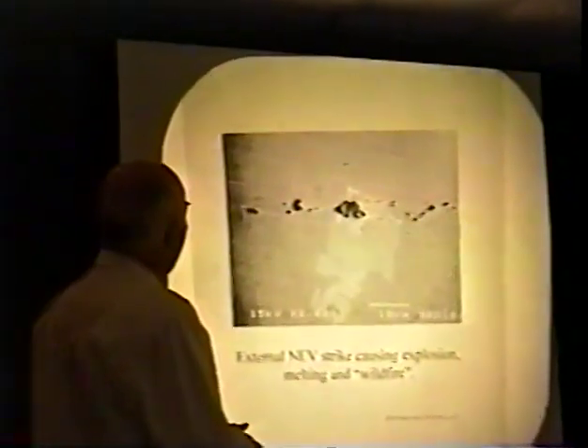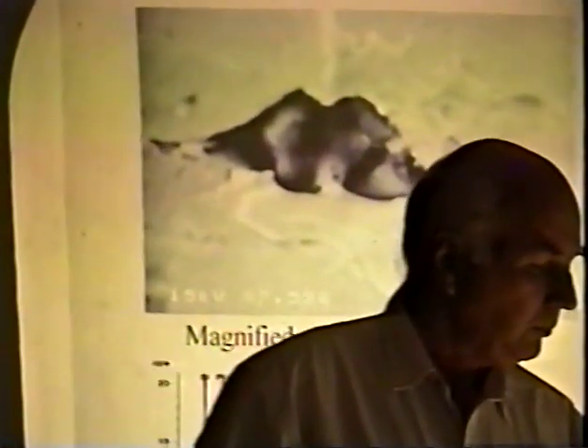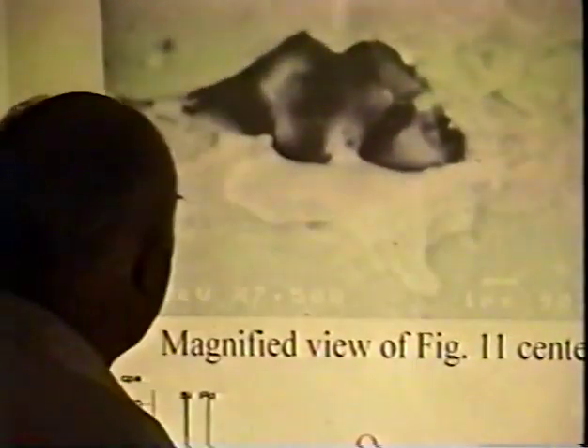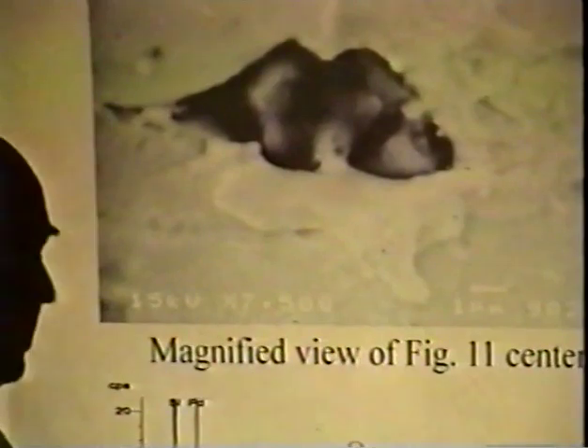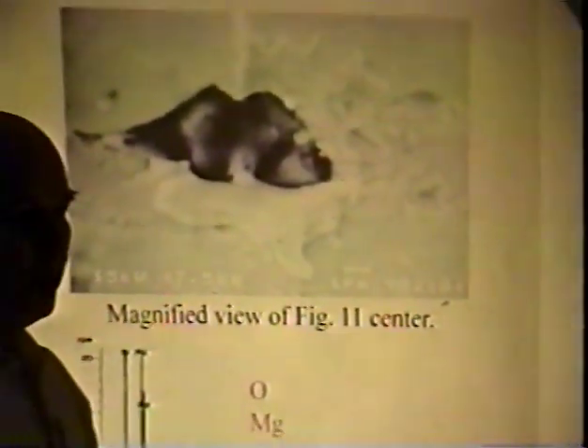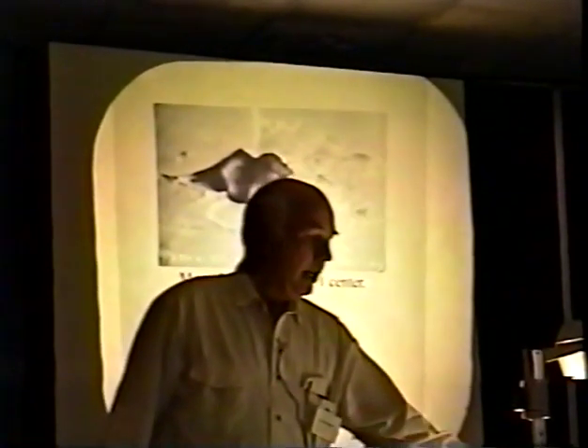Now, it's more evident in things like this, where you purposely bombard the surface, analyze this particular area, you'll see there's something happened here, some kind of little spreading of energy. Not trying to define what it is in this talk. I'll say when you get up and closely analyze that particular sample, look at that trash pile here. You'll see there's a lot of melted laid-back material, and what you find is oxygen, magnesium, aluminum, silicon, and calcium, typically. More dirt. The dirt was not in cracks like that by the hundreds, but it did show up suddenly here.